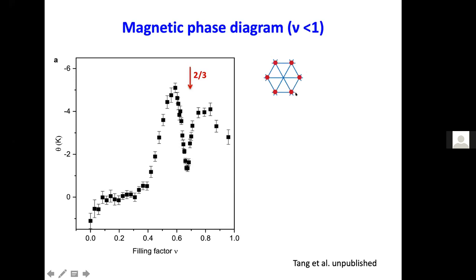So there are two possible exchange pathways. One is the super exchange, like what we talked about for Mott states, and that gives us theta on the order of half a Kelvin.